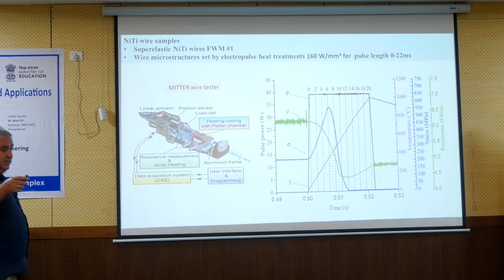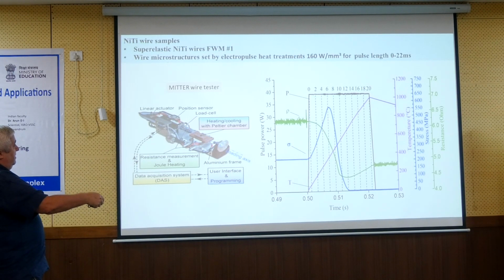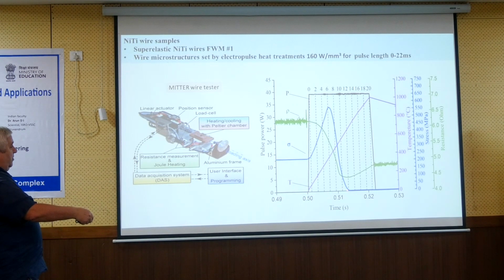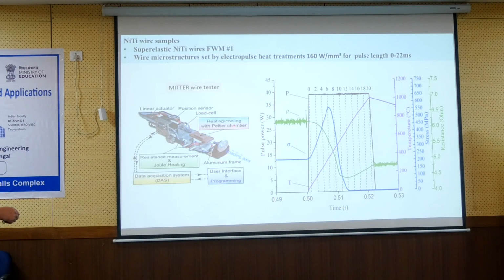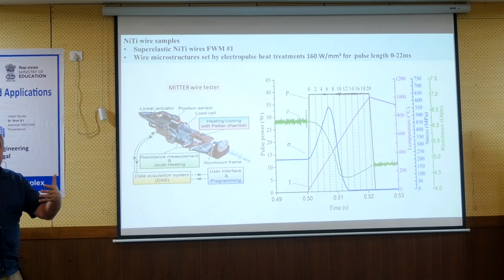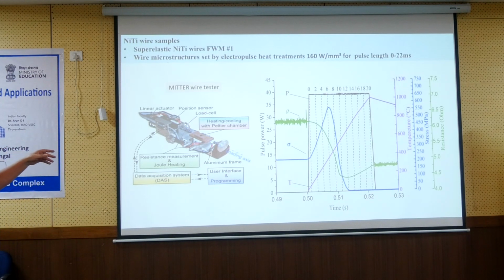This is actually the situation we discussed yesterday. When you have the wire in martensite state and fix the length and start to heat it, the stress goes up, but only to some maximum, like 500 megapascal here, and then it decreases to 0. At the same time, we are measuring the electrical resistance. At first when you are heating, nothing is happening, but then the resistivity goes down. So some process occurs here, which is related to the change of the electrical resistance of the wire. So we have some control over what is happening during the heat treatment. There is a paper published, listed here, which analyzes what is happening during the heat treatment, but I will not go into the detail of that.